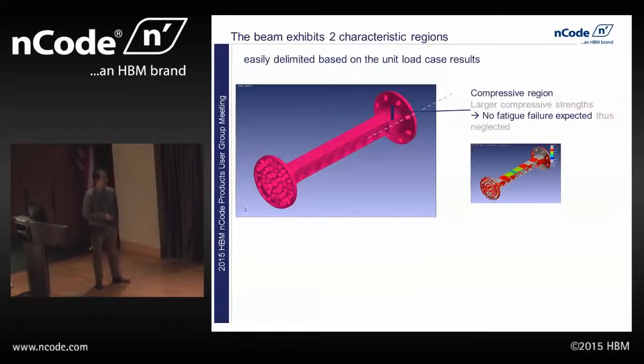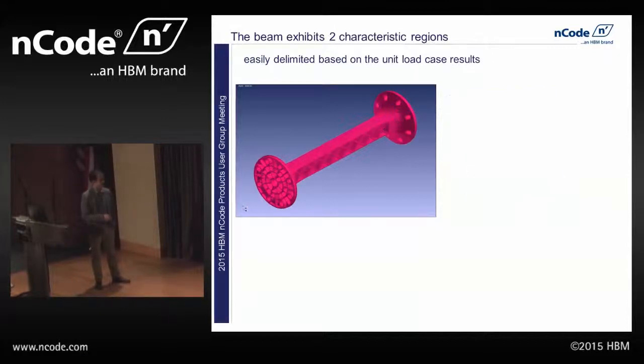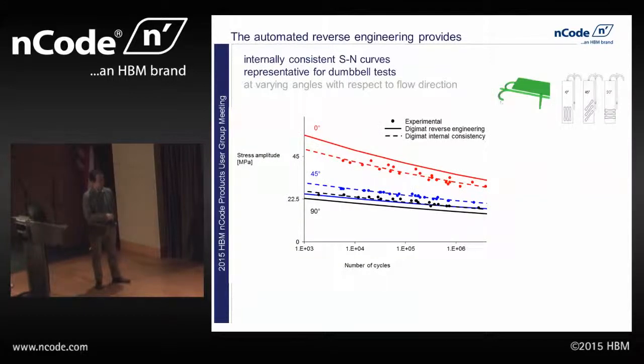So if we go ahead and look at our analysis here, one thing that's worth mentioning that maybe I should have mentioned earlier is, when we're looking at these materials, at least at this level, we're only looking at the tensile strength of the material. And that's really important when you talk about plastics or these composite materials because they tend to have a very different strength in tension versus compression. They tend to be a lot higher, a lot stronger in compression.